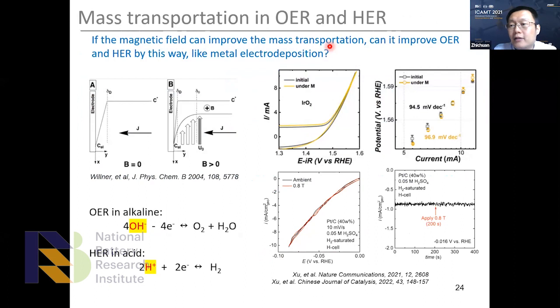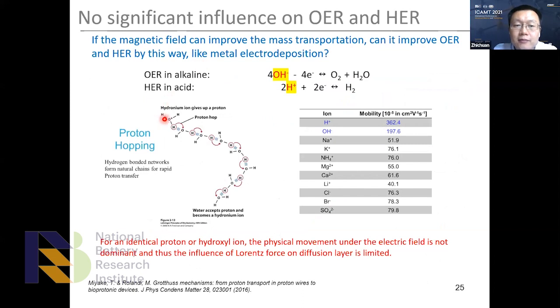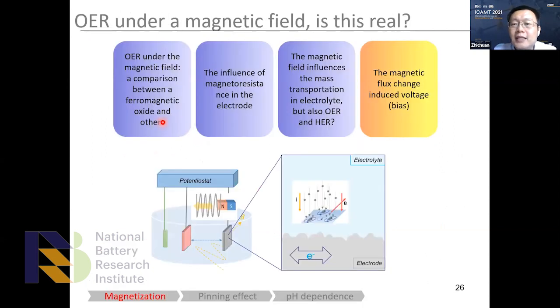So back to the OER. And also, I would like to include HER here. I would say the magnetic field will not affect it, because the precursor, although we write precursor like ions, in fact the precursor is water, not charged ions. This is very unique for water, because water is the solvent and also the reactant. So we know that the ions are transported within the water by proton hopping. It is not physical movement. So in this case, the Lorentz force will work very little on the mass transportation as we imagined it. So we can confirm the mass transportation won't play that important role over there.